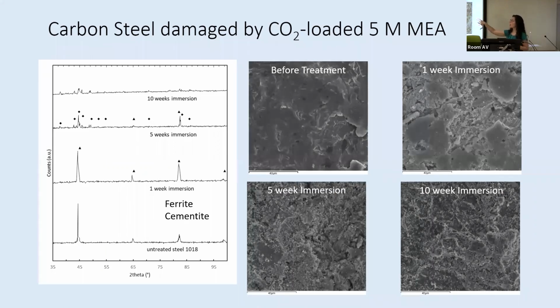We've got a mixture of two different forms, ferrite and cementite. The more labile iron from the ferrite becomes available, and we're starting to see that that's the part being oxidized away. You can already see in 1 week from an XRD scan on the left, which indicates the crystal structure, and we won't get into the penetration depth and things, that after 1 week you start to see a little bit of change from the original structure. But as you hit 5 weeks, you can start to see an increasing presence of cementite. Cementite is indicated with the diamonds. I think they got lost, and the triangles are the ferrite.